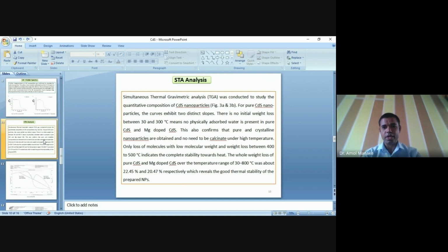For pure cadmium sulfide nanoparticles, the curves exhibit two distinct slopes. There is no initial weight loss between 30 to 300 degrees centigrade, meaning no physically adsorbed water is present in the synthesized pure cadmium sulfide nanoparticles as well as Mg doped cadmium sulfide nanoparticles. This also confirms that pure and crystalline nanoparticles are obtained and there is no need to calcinate under high temperature.